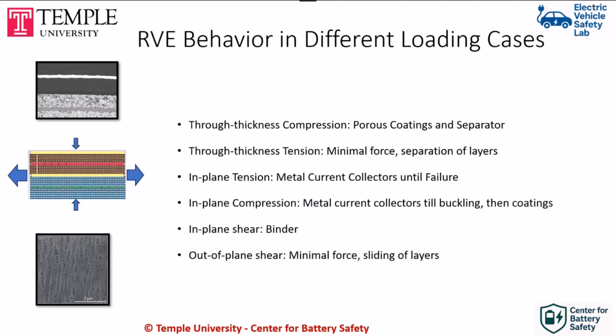If you have in-plane tension, then the metal layers will start to contribute. So the main thing that will control that behavior will be the metal layer. And then these are very brittle foil materials that can fail very early. If you have in-plane compression, then in the beginning, the metal layers will contribute until they buckle. And then after they buckle, then those coating layers will start to contribute. Now, if you have a sliding of the layers, like the shear, in-plane shear will cause binder failure. The only thing that keeps the layers together is binder. If you have out-of-plane shear, the layers will just slide on top of each other unless you have friction or compression that causes friction.